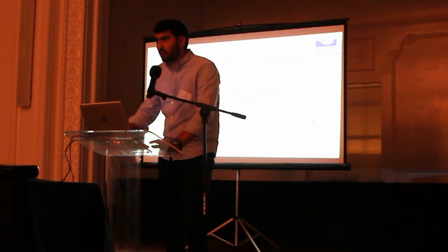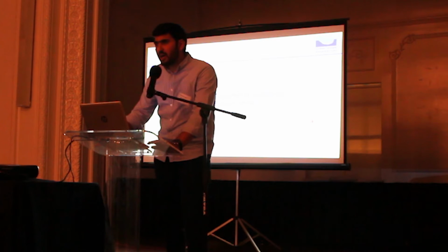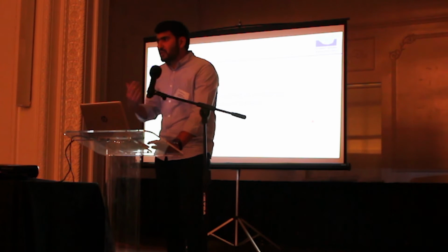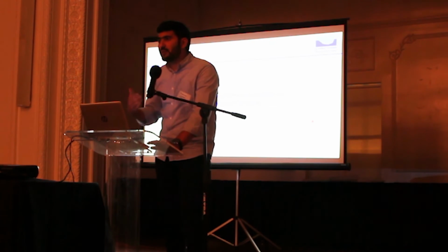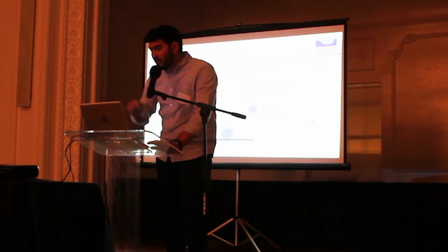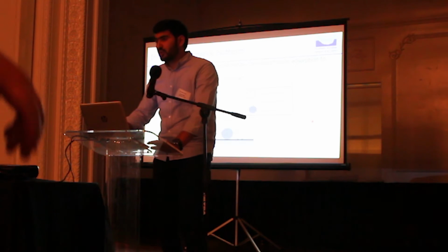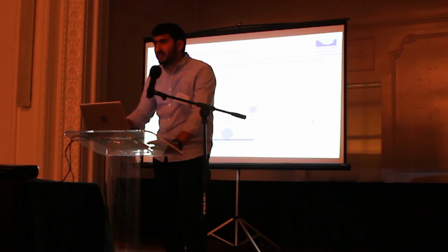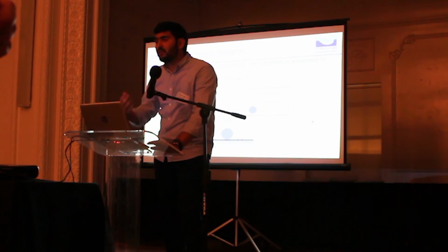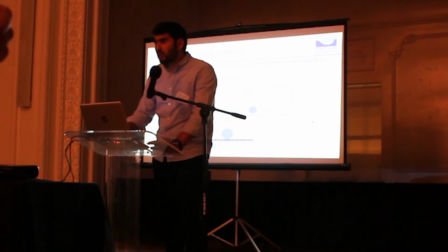All right, so after looking at how we can reduce corrosion by the presence of iron carbonate scale, now we're going to look at how we can minimize corrosion by adding chemical inhibitors. As I mentioned earlier, when the corrosion rate becomes increasingly high, chemical inhibitors are commonly utilized to minimize corrosion. The mechanism of corrosion protection by inhibitors is generally modeled by the physical chemical adsorption of the inhibitor molecule to the metal surface. This adsorption phenomenon depends on the chemical composition of the inhibitor molecule, the environmental temperature, and the electrochemical potential at the metal solution interface.